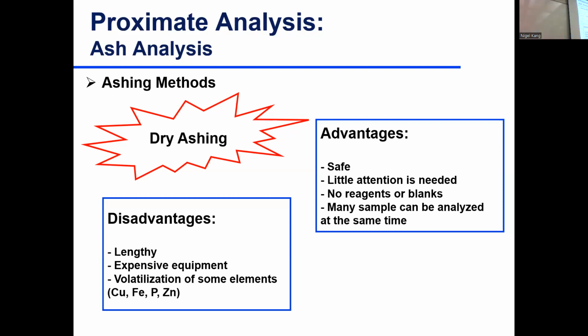It's so lengthy, time-consuming method, and if you don't pay attention to complete ashing or incomplete ashing or good sample preparation that cause loss of your sample because of foaming, because of smoking or burning, or because of spattering, then you need to repeat this assay, which is really, really time consuming. The other point is that you are doing dry ashing at really, really high temperature, 500 degrees Celsius. At this high temperature, there is a possibility of volatilization of some elements like iron, like phosphor, like zinc. So still there is a possibility of underestimation.